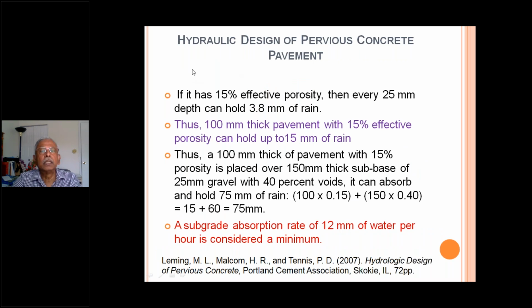This shows a hydraulic design of pervious concrete. It has 15% effective porosity. Then every 25 millimeter depth can hold 3.8 mm of rain. Thus, 100 mm thick pavement with 15% effective porosity can hold up to 15 millimeter of rain. Hence, a 100 millimeter thick pavement with 15% porosity placed over 150 mm thick sub base of 25 mm gravel with 40% void, can absorb and hold 75 millimeter of rain. The calculation is shown here. The subgrade absorption rate of 12 mm water per hour is considered a minimum.